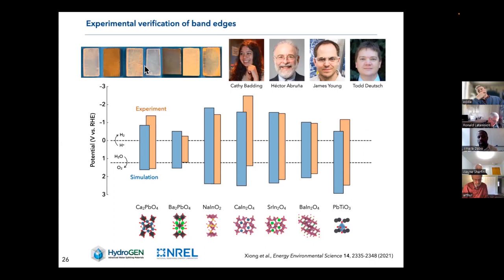So we were very fortunate to be able to collaborate with a group at the National Renewable Energy Lab that drop cast the powders that were synthesized into thin film. And based on that, we're able to do photoelectrochemical characterization to determine the range of energy that we have for these material in terms of their absorption of solar light. And you can see that we do fairly well for most of the compound, except for some of them, for example, for this calcium indate, where you see a shift in the energy.